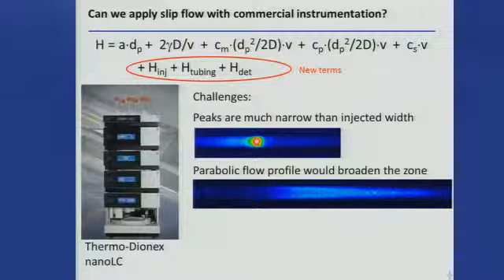And then applications, so we've published some papers using commercial instrumentation. We have to be concerned about Poiseuille flow through the tubing. If you look carefully at this, there's tubing all over the place. So after the column, we can't let it go through tubing. This is a picture we took in our lab of Poiseuille flow. We did isoelectric focusing to get a really sharp peak. Apply a little bit of flow. It really is a parabola. You can tell that. And it just stretches out right away. So you've got to be really careful when you go into tubing. You want to go from a big diameter to a really tiny diameter so that it goes through there in no time at all. Shortest tubing that you can get by with in order to minimize this.